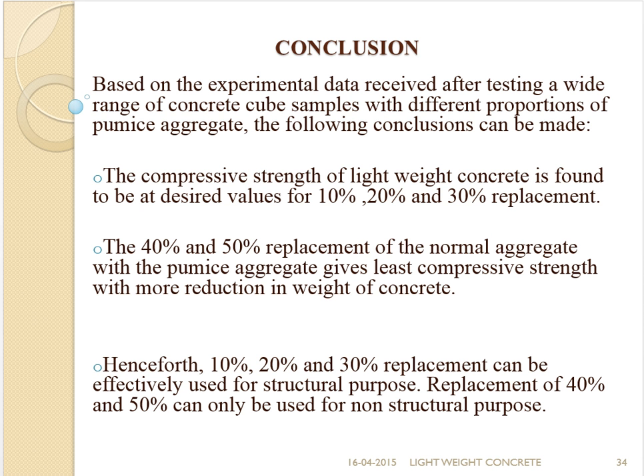We have arrived at the conclusion from this project that the compressive strength of lightweight concrete is found to be at desired values for 10%, 20% and 30% replacement. But 40% and 50% replacement of normal aggregate with pumice aggregate gives the least compressive strength with more reduction in weight of concrete. Henceforth, 10%, 20% and 30% replacement can be effectively used for structural purpose, whereas the replacement of 40% and 50% can be used for non-structural purpose only.